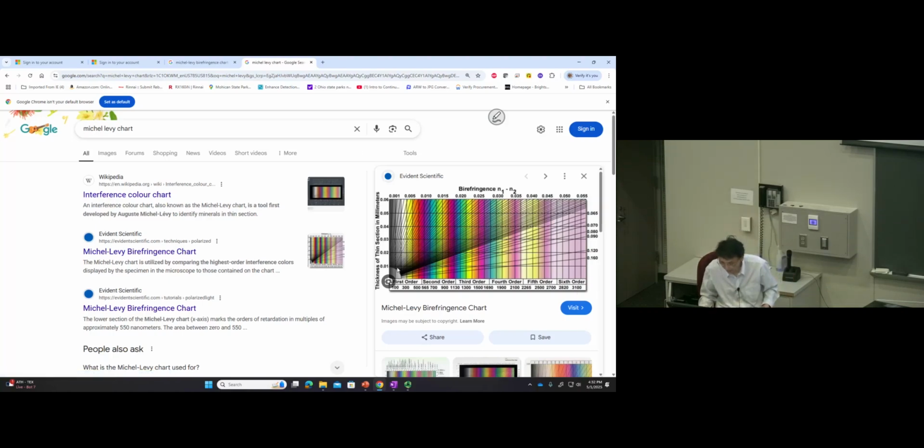So, to cut it short, there is a way to tell the degree of chain orientation. And it turns out that the degree of chain orientation is precisely correlated with how much you're stretching the polymer. And how much you're stretching the polymer is how much stress occurs. So it's firmly established that through this measurement, you could read the stress spatially if you have a microscope. The only thing left is the resolution of your microscope.